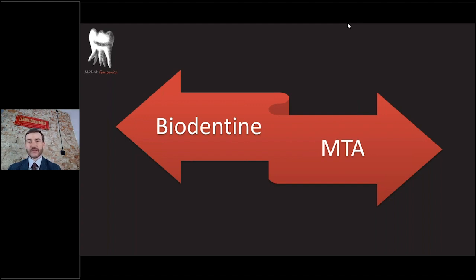Another point is that the solubility of the Biodentine is lower than the solubility of the MTA. And why is it like this? Because to mix and prepare Biodentine, for one portion we are using just 5 drops of the special liquid, which is in the set with Biodentine, and nothing else. We are just putting 5 drops. So in the whole mixture there is a very small amount of water. So the solubility of the Biodentine is less.